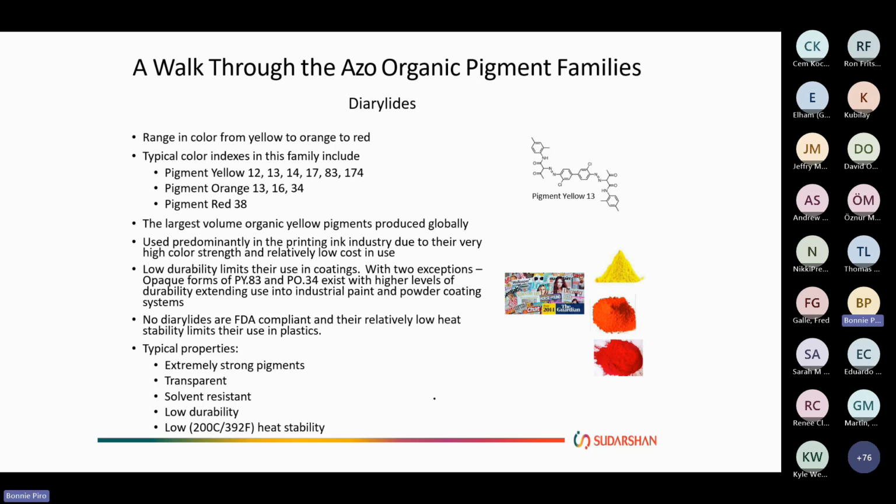Diarylides are not FDA compliant, so that should be something to take into consideration in your formulation and your attribute list. And then, of course, their lower heat stability limits them, so they are much more limited in plastics areas.